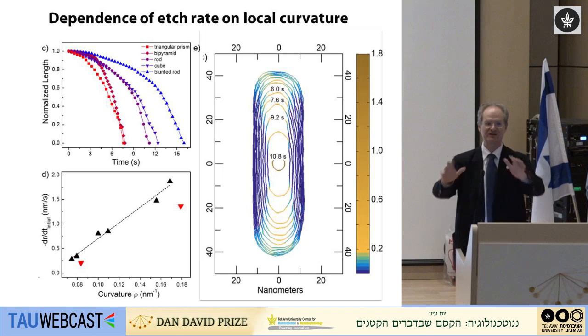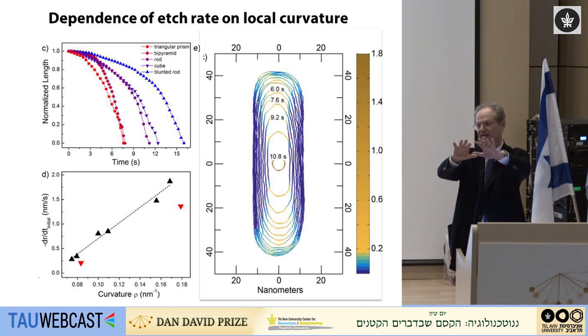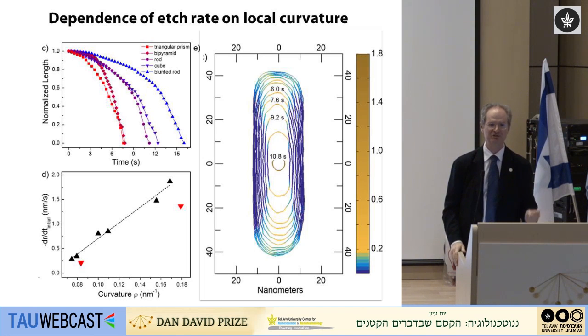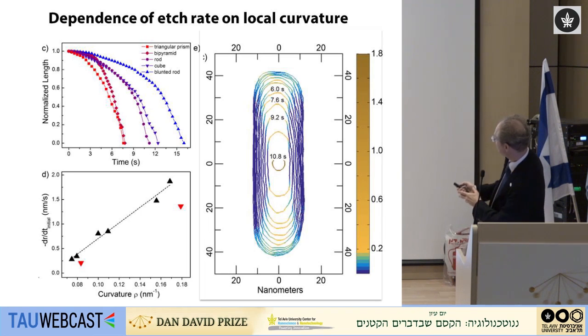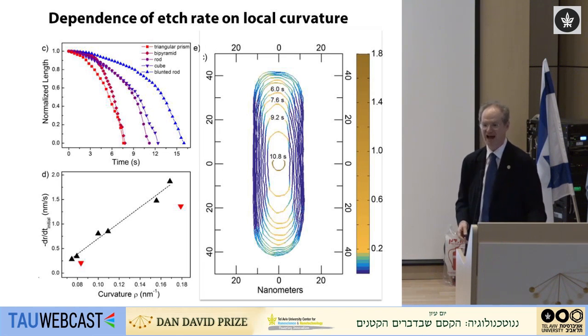And that's easy to understand because a curved crystal has a curved facet has essentially broken or weaker bonds at it, so it becomes a spot that can be picked off more easily by the etchant. And so that's quite a simple idea. So we can make this kind of contour plot that shows, again, how a crystal disappears. Sequentially, these are each units of time, and what you can see, of course, is that it appears as though atoms are being lost from the curved end a lot faster than they're being lost from the flat side.